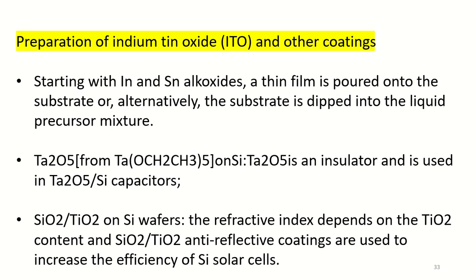The next application is the preparation of indium tin oxide (ITO) and other coatings. Semiconducting ITO is widely used as an electrode, especially as thin film coatings. It is used as a coating on glass for energy control of buildings since it transmits visible light and reflects infrared radiation. The coatings are prepared by the sol-gel method starting from indium and tin alkoxides; a thin film is poured onto the substrate or the substrate is dipped into the liquid, and the coating is then processed in situ, giving finally an amorphous, thin, transparent, adherent layer.